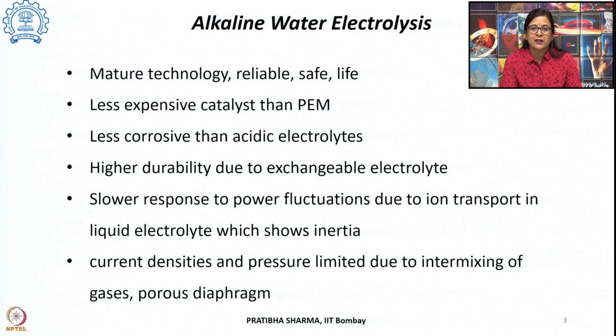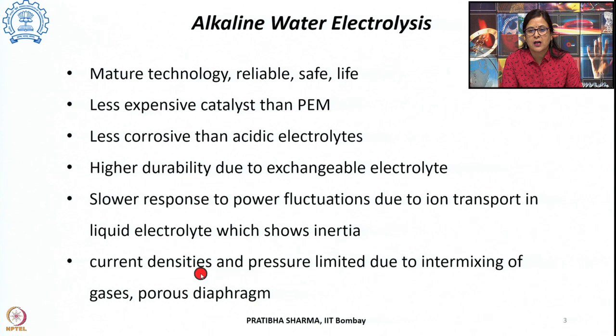However, since hydroxyl ions are transported across the separator, the process has a slower response to power fluctuations due to inertia in liquid-phase ion transport. The current densities and pressure are also limited due to intermixing of gases, as the porous diaphragm cannot operate at higher current densities or pressures without crossover of gaseous products.